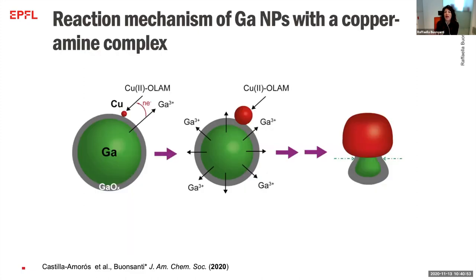And so we could explain eventually what happens when exploring the reactivity of gallium at the nanoscale. So the gallium is liquid, we have a shell of oxide. There are some micro cracks. I mean, these gallium ions somehow pass through these small cracks or pinholes in this oxide shell. The galvanic replacement reaction occurs, but because of the presence of this oxide shell, there is no alloying, but instead we have the formation of these dimers.